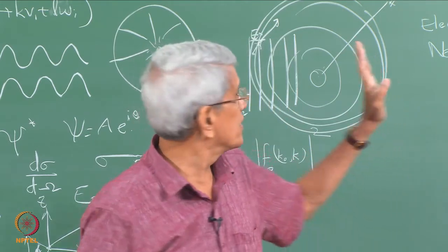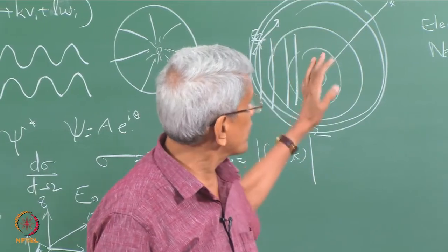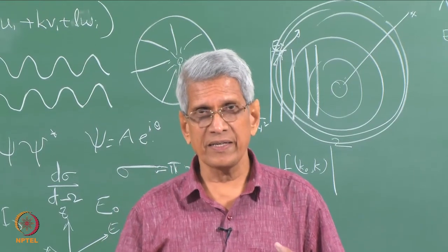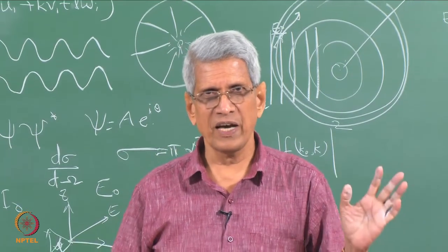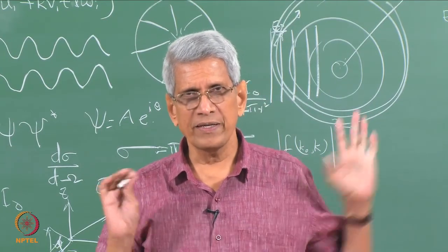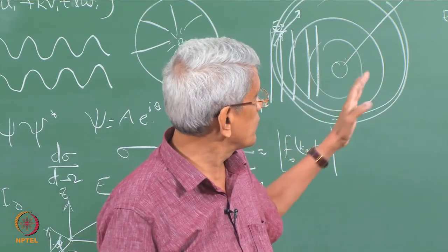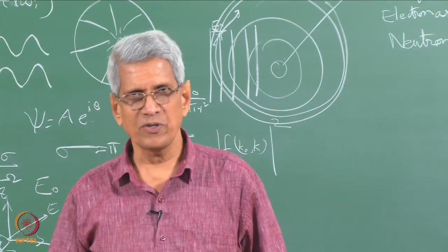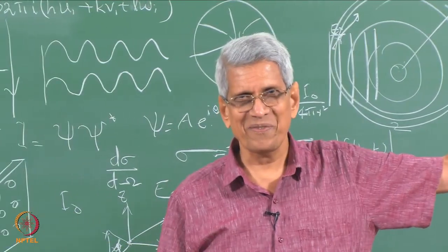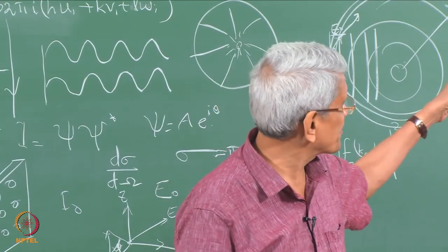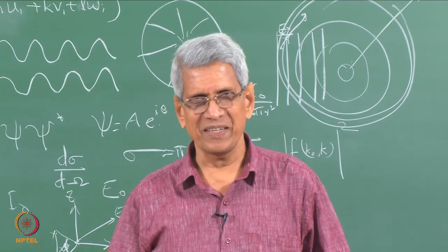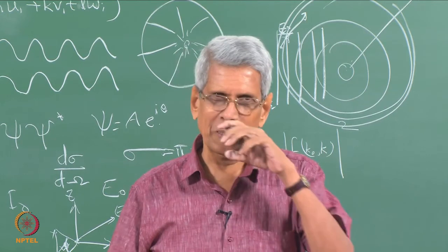That is in the case of X-ray. In the case of electron, what is essentially going to happen is that it is interacting through the Coulomb interaction with the positive charge or the negative charge, or the screened potential. Depending upon that, it will give information about how the potential distribution is going to take place. Neutron has many more information than that, but it does not talk about potential distribution. It talks about the nucleus, isotope distribution, then magnetic moment, how it is getting distributed. This sort of information we can get.